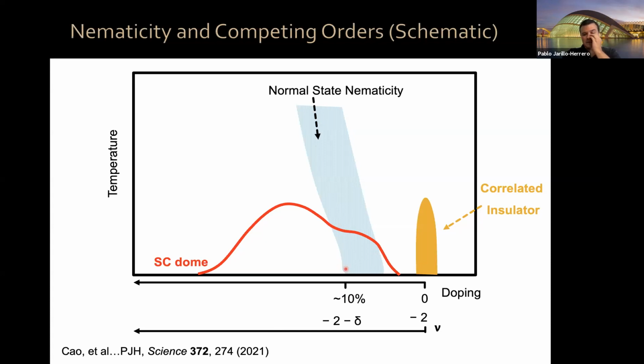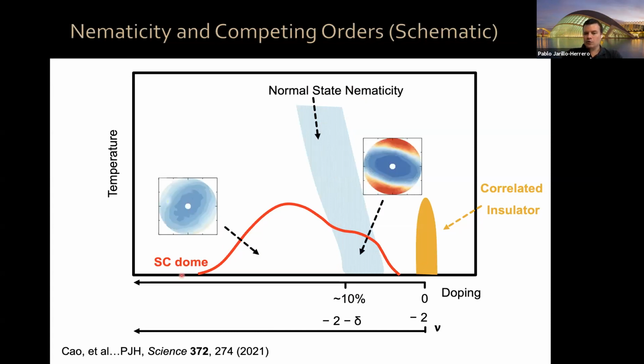As I showed you, at finite magnetic field. Now, this region of resistivity that competes with superconductivity has normal state nematicity, anisotropy in the normal state. Now, the superconducting dome, everywhere in the phase diagram, you also have nematicity. But the nematic axis can change direction. In particular, the nematic axis seems to change direction weakly in this region, but when you dope into this region where we have this normal state nematicity and this competing phase, actually it changes rapidly there.